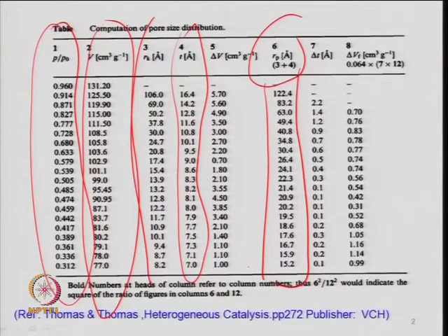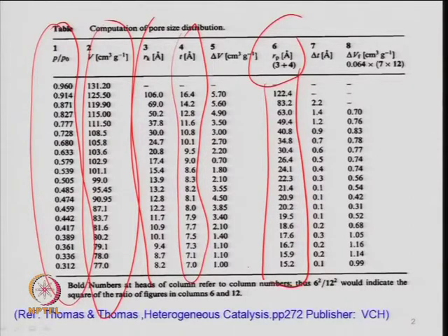If you want to get further analysis, you can find out, between two pressure steps, what is the difference in the volume desorbed, because we are talking about desorption data here, and simultaneously what is the decrement in the condensed layer thickness. So, that is delta t, which can be obtained between two successive layer thicknesses. It is related to the decrement in the fractional volume, because in that delta t layer, what is the volume of the liquid gas which is desorbed can be calculated.